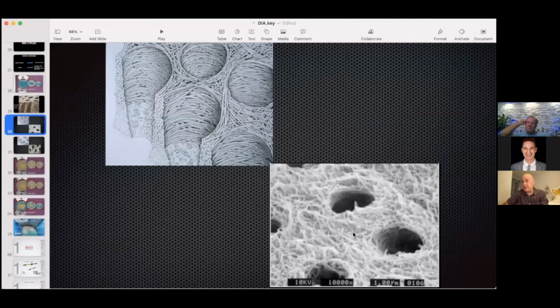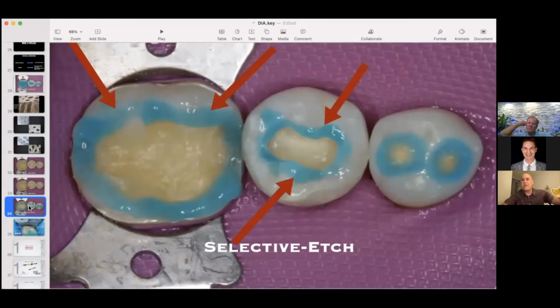Rather than bond strength. You still have the walls, and most important, you still have enamel. If you have enamel, your bond strength is not that important on that deep pulpal floor. You have walls and you have enamel. So when you look at this, this is fantastic. Oh, I'm going to cover it with glass ionomer. Yeah, your bond strength is not going to be good, because you just covered that dentin with glass ionomer.